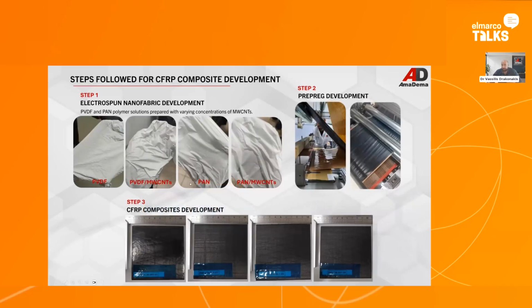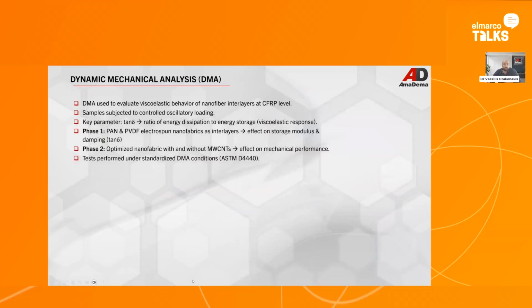Here we have different PVDF-based and PAN-based nanofibers together, either plain or with carbon nanotubes. And you can see how the process of the prepreg was done in order to use them in different CFRP composites. So DMA, dynamic mechanical analysis, was used afterwards in order to evaluate the viscoelastic behavior of the nanofiber interlayers at CFRP level. So basically the CFRP performance with and without the nanofibers.